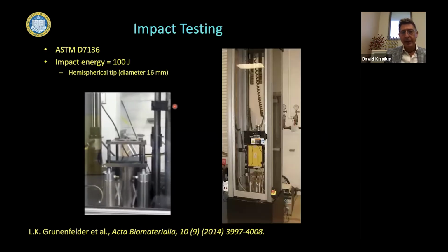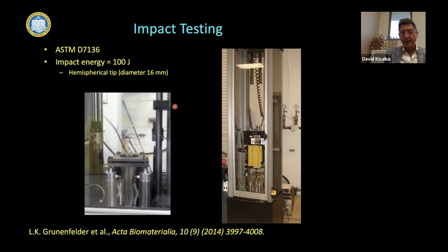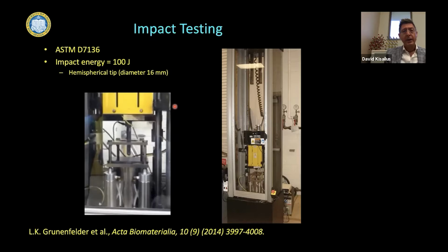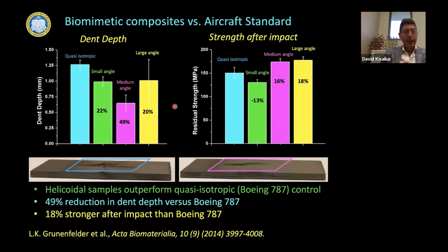And we've subsequently taken those helicoidal panels and performed, for example, drop tower testing on these carbon fiber composites. And what you can see is that comparing the helicoid architectures, where I have small, medium, and large angle, to what's used, for example, in the Boeing 787, quasi-isotropic, you can see the dent depth, the damage to the surface of these panels is significantly less. So what it's telling us is that damage is being spread laterally by this crack twisting versus getting through thickness damage.